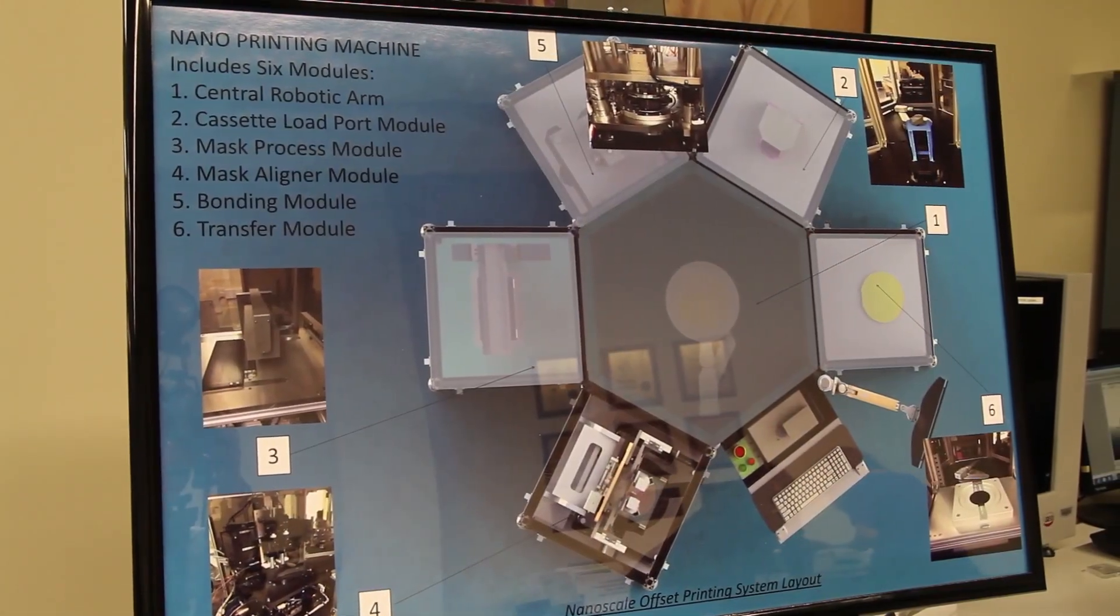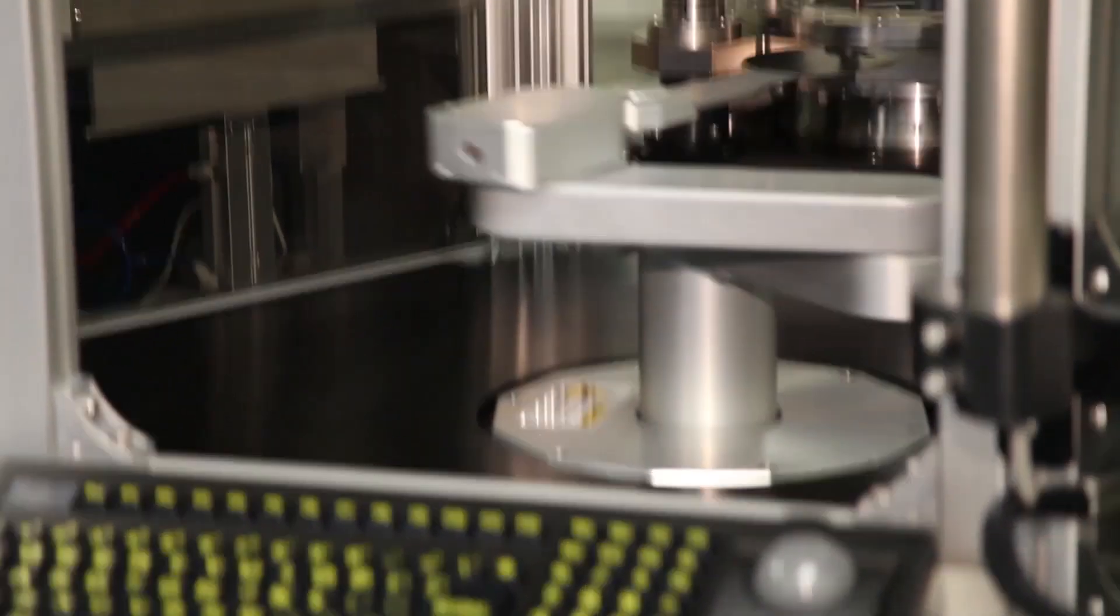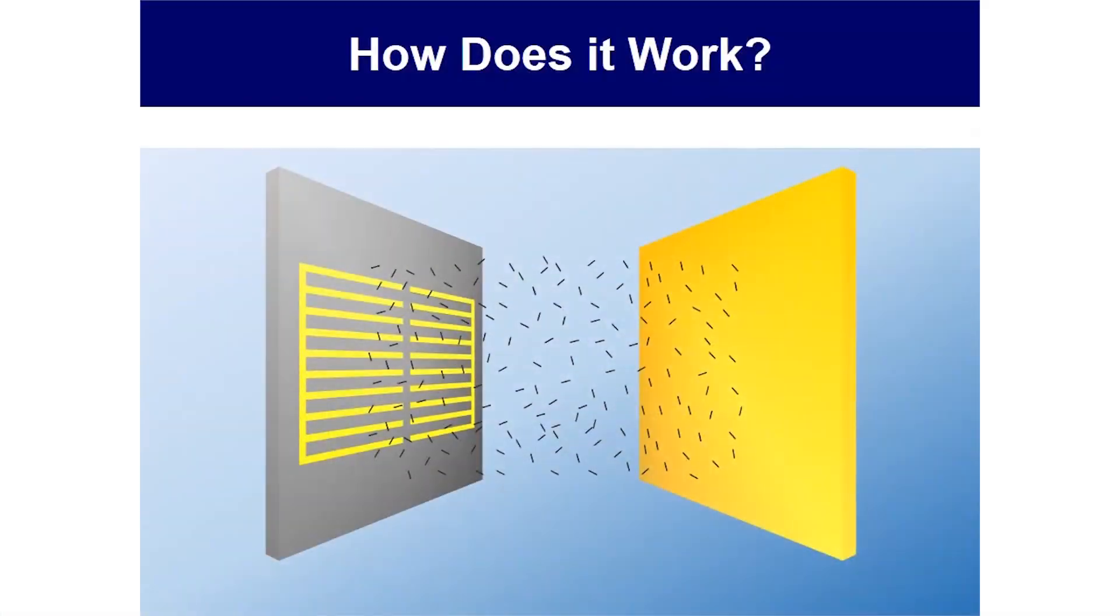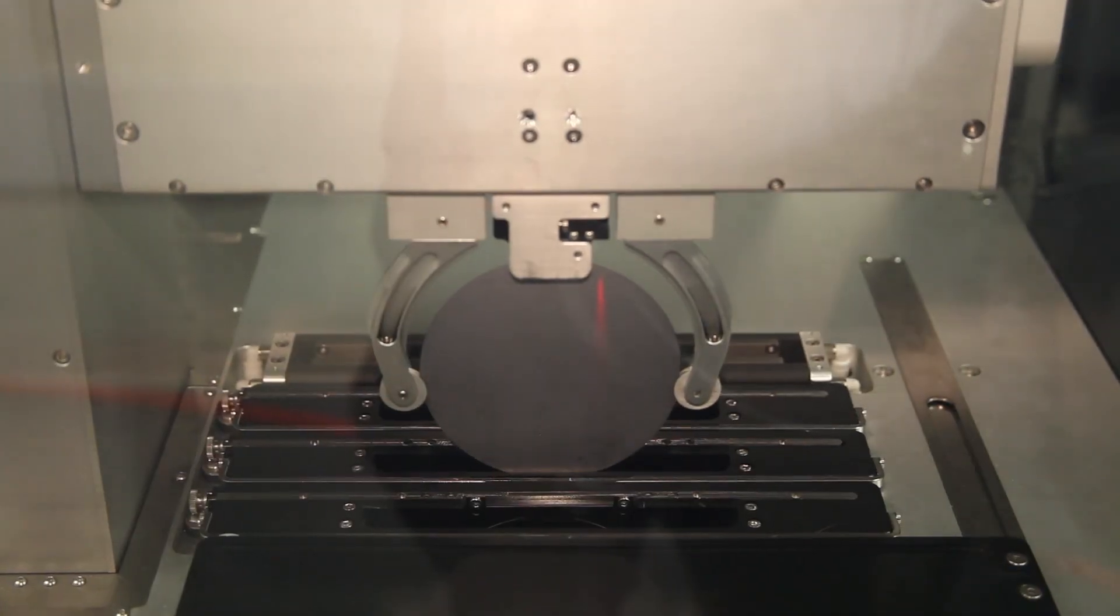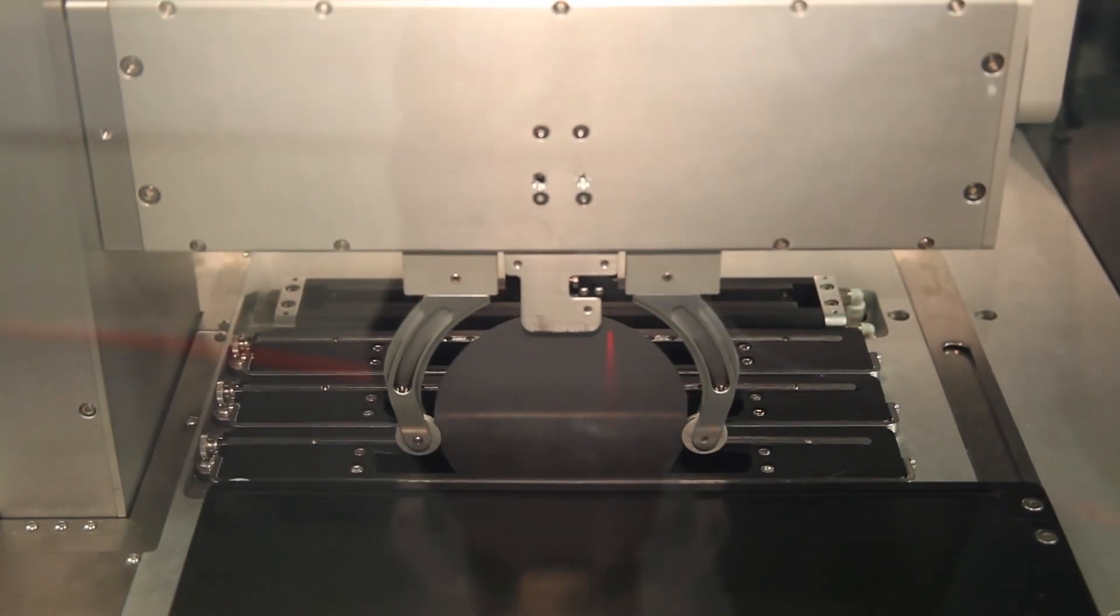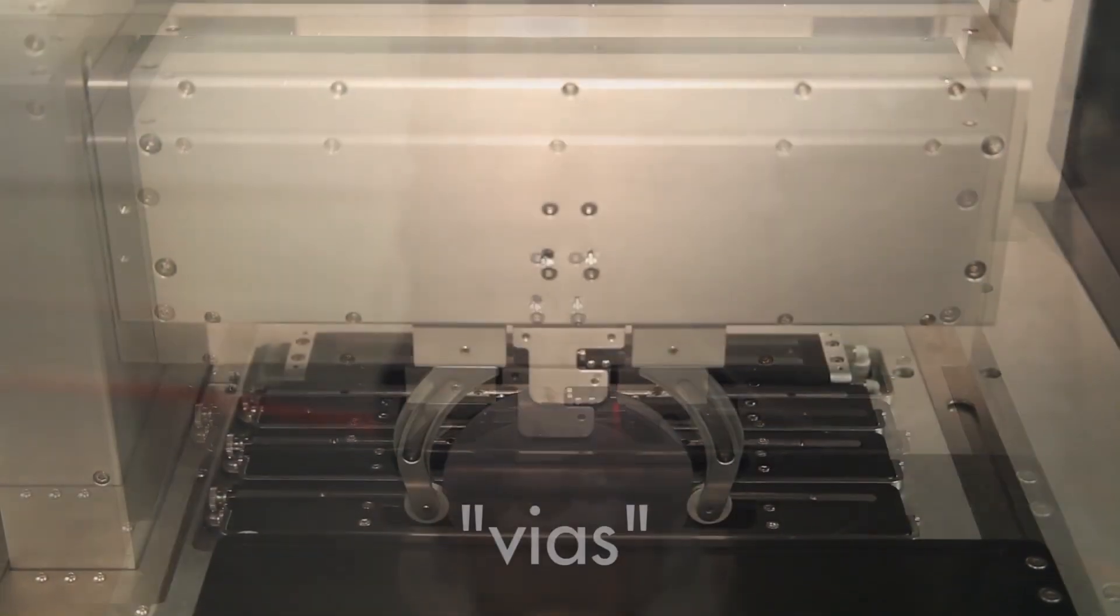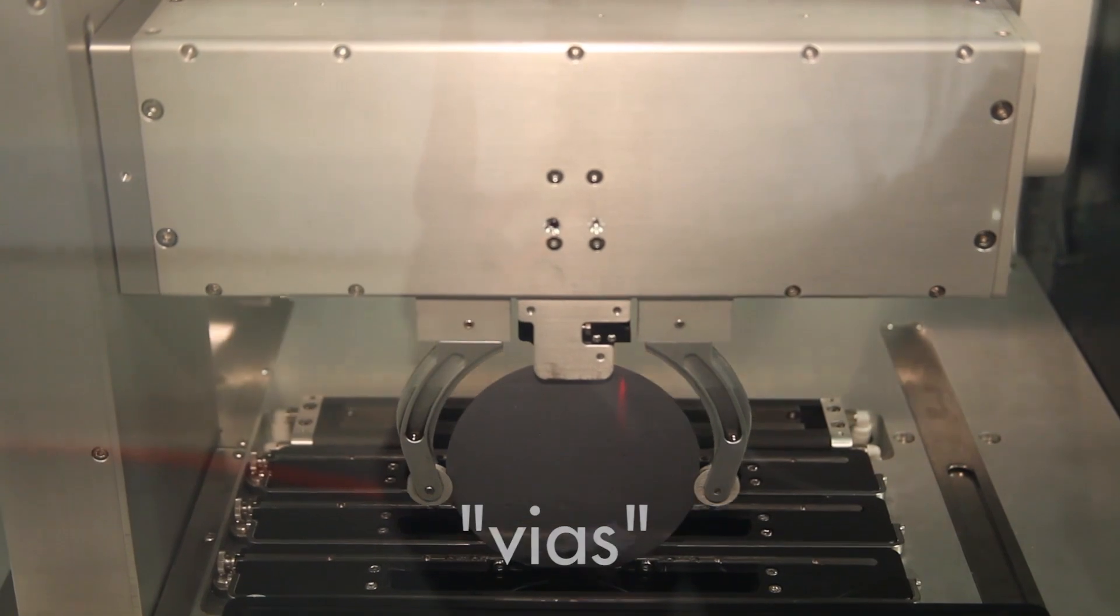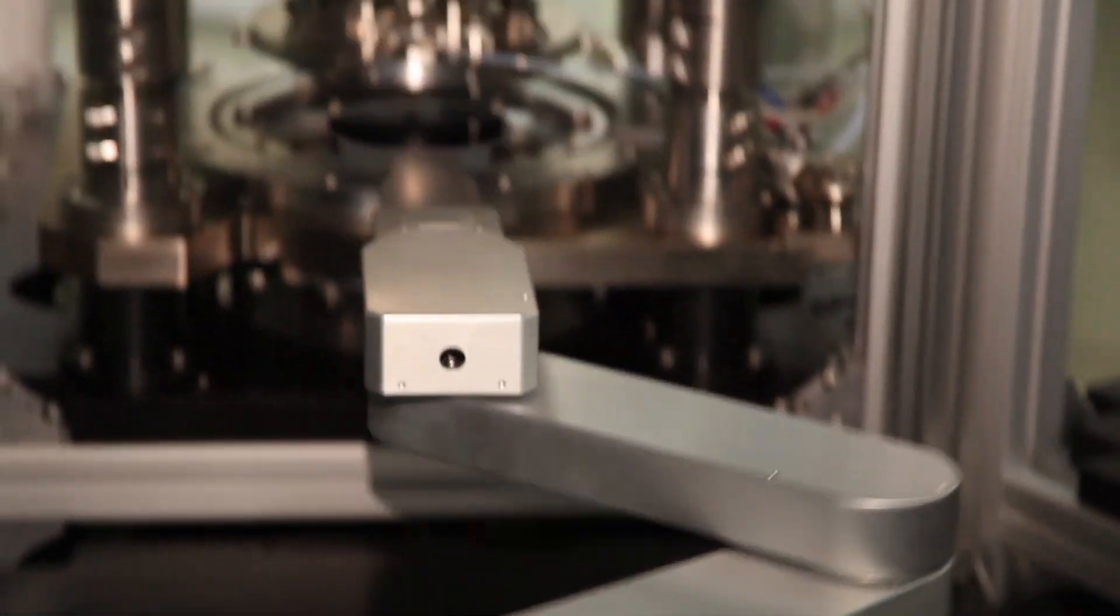Nano-ops is an automated cluster of tools designed for the stepwise assembly of nanoscale building blocks such as nanotubes and nanoparticles into functional materials. The process begins with the preparation of a template using electron beam and photolithography. Once prepared, the template is then moved into a liquid solution in which charged nanoparticles are guided into grooves and spots on the template, called vias, through an applied electric field.